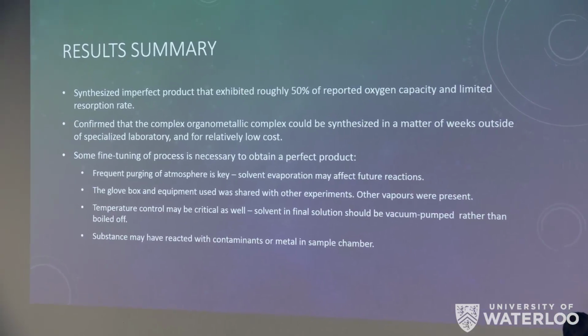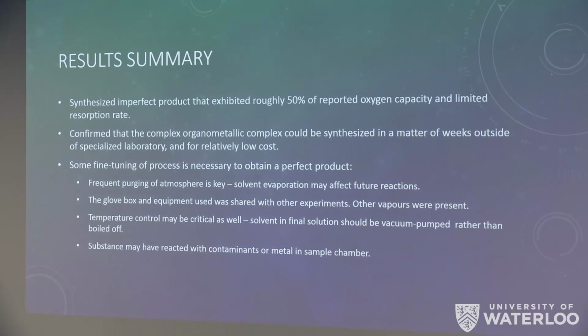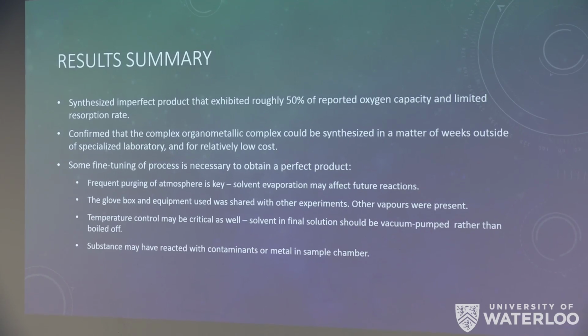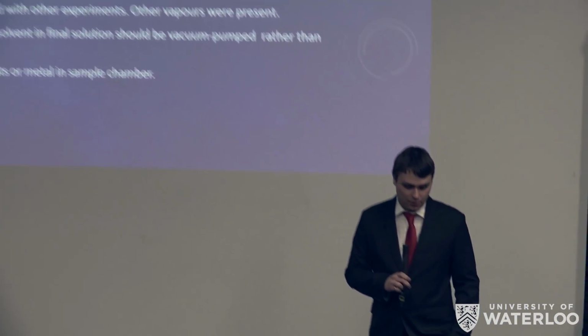So in summary, we did observe the basic mechanism expected from our product, which was the reversible absorption of oxygen and water vapor. The cost was kept relatively low for an experiment like this at around $21 for 60 milligrams of product. This cost is strongly hampered, however, by the extremely small quantities we could produce. Scaling up production would lead to a much decreased cost for the obvious reasons, especially with the time and equipment to synthesize our costliest precursor, bipyrrolidine, from simple monomers.